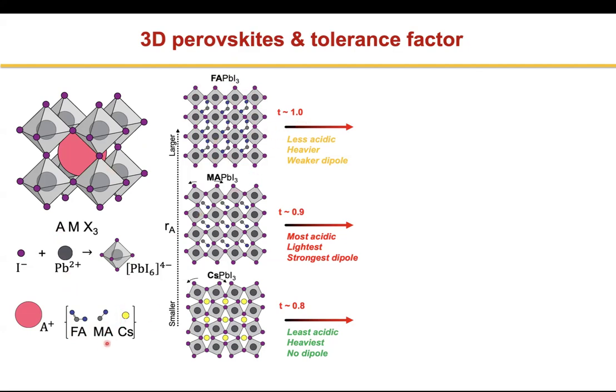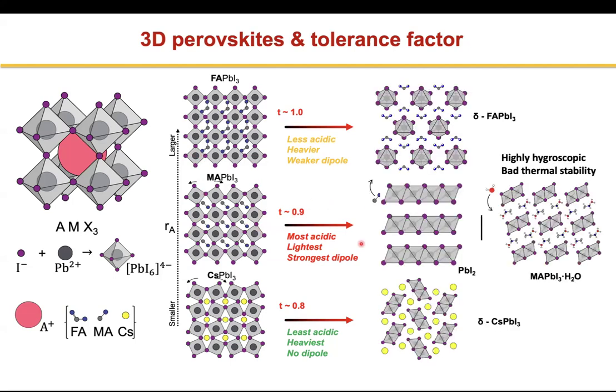Then if I take MA instead of FA, I have a tolerance factor of 0.9, and if I take cesium, I have a tolerance factor of 0.8. Now, a perovskite is anything that falls between these ranges. You can see that this is right on the edge. It's a little bit too big, this is a little bit too small, but this material is absolutely perfect. And so methylammonium lead triiodide really works the best, and you can make a very nice perovskite with it. Whereas in the case of FAPI and cesium lead iodide, you can't make a really good perovskite. In fact, at room temperature, it exists in something known as the delta phase, or the yellow phase. You can see there are these separated islands of perovskite-like structures, and that's known as a delta phase. It's a polymorph of your formamidinium lead triiodide.